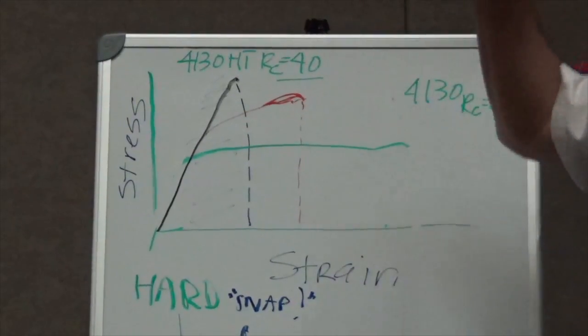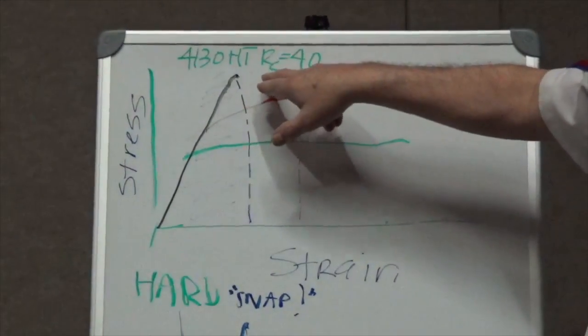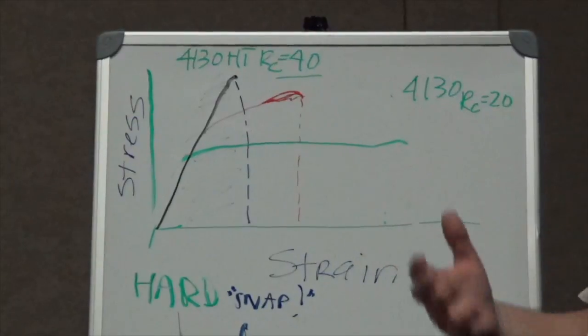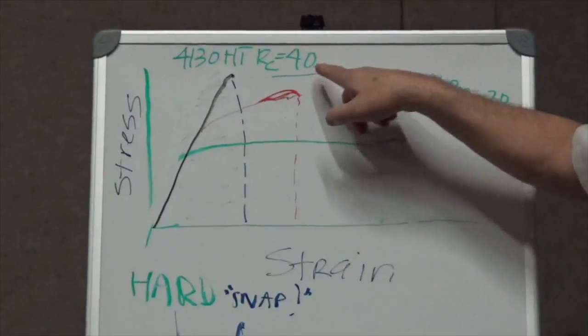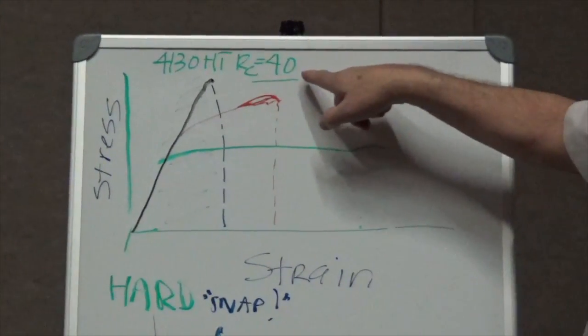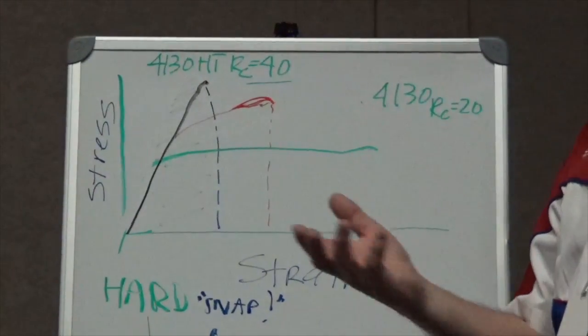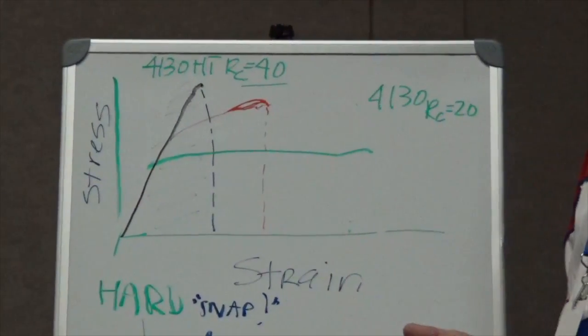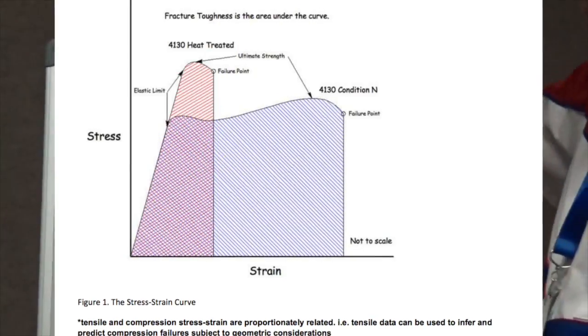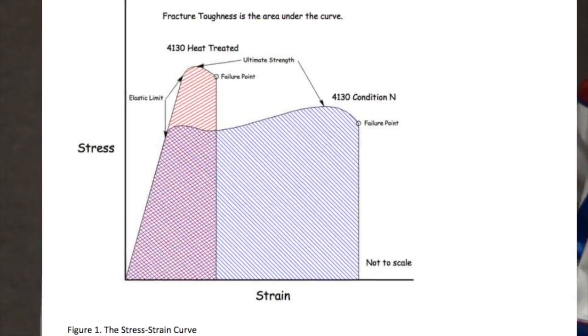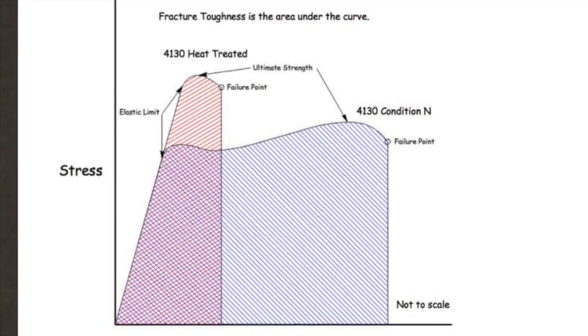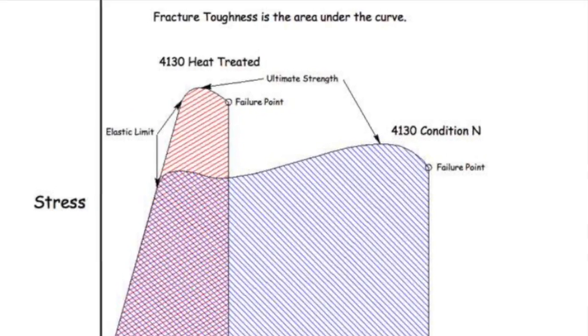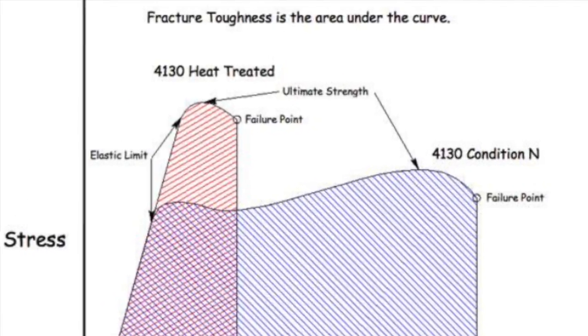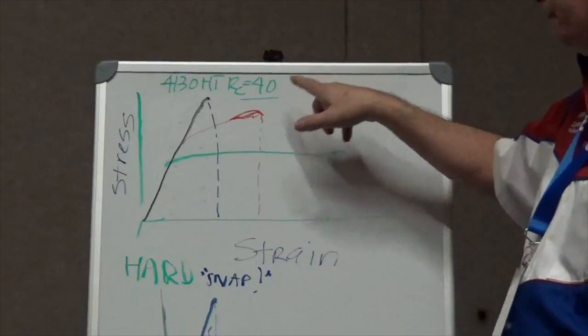But for steels, most steels are in what is referred to as a C range. So in this case, let's say that you took a chromoly sample and you heated it to where it's hard. If you were to talk about the tensile numbers, the numbers that everybody quotes in their bicycle tubing things, or in their aluminum tubing things for that matter, this would equate to somewhere around 140,000 pounds per square inch of strength, maybe a little more than that. That's pretty hard for chromoly. In fact, it's probably more than that.